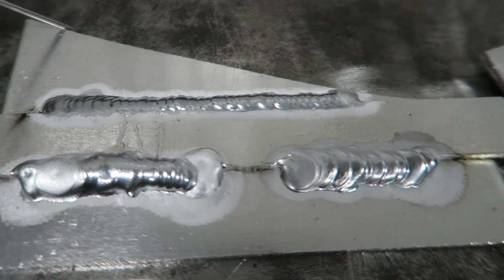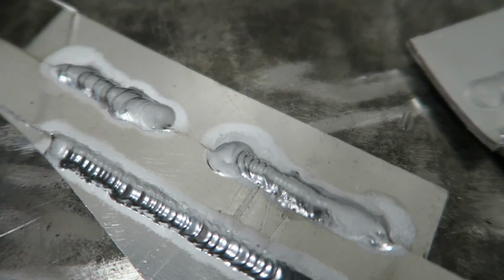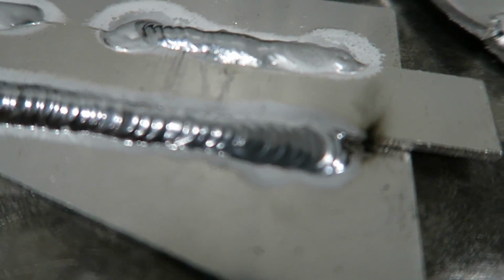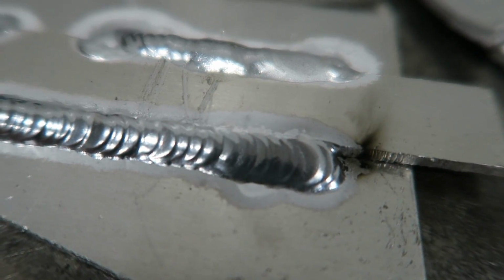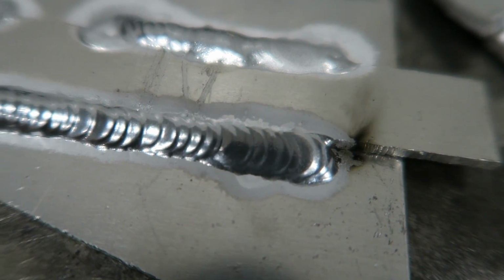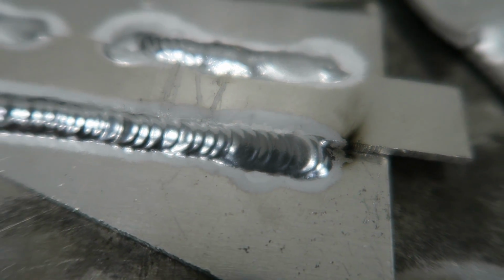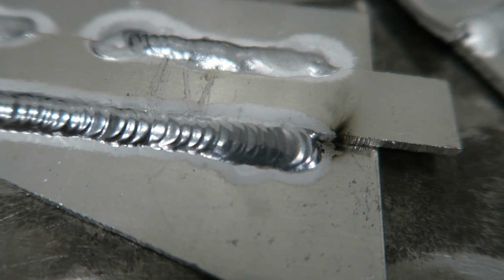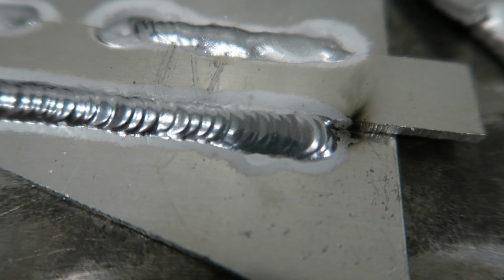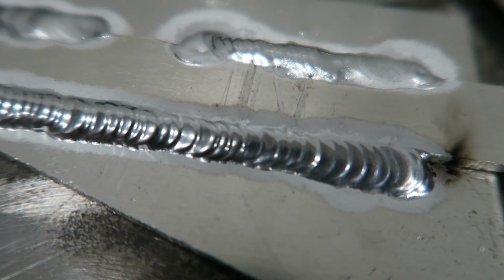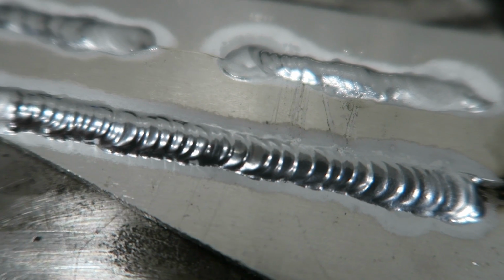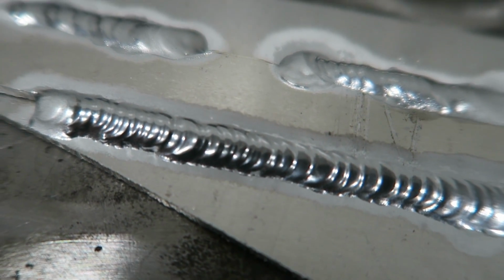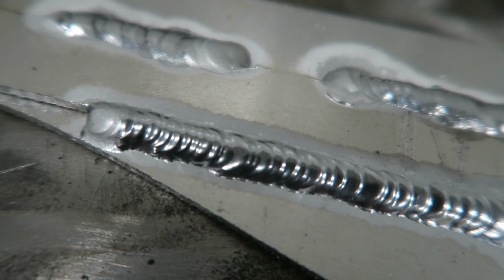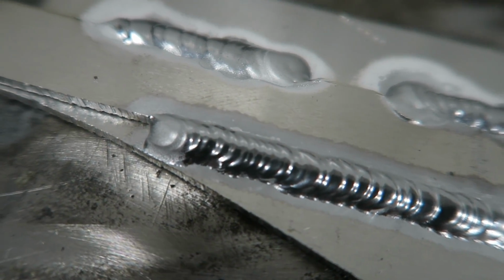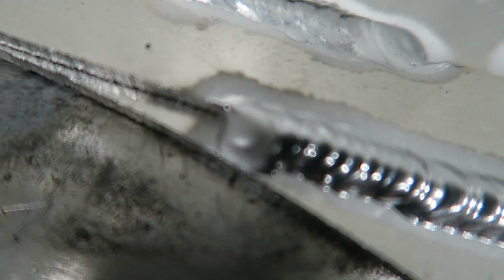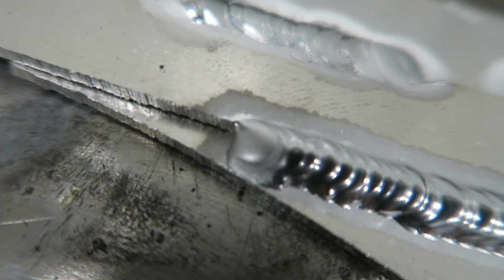So now let me show you what a good weld looks like. Again, this bead is accentuated so that you could see it. So we started out with a thicker filler rod. We started here. The part was still super, super hot, so we had to back off the heat real quick because that bead was getting too big. And then as you go down the bead, you can see the white stripes on either side, the cleaning action. We were exactly where we needed to be. We had exactly enough filler metal. We had exactly enough penetration. And at the end, we didn't have a crater.